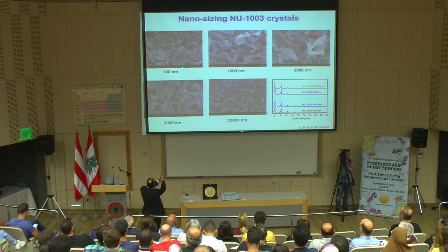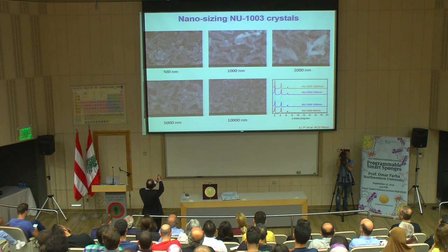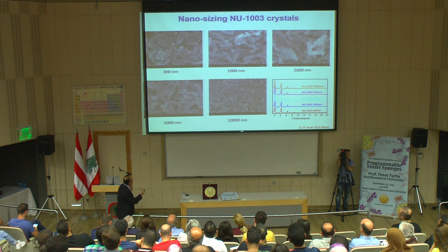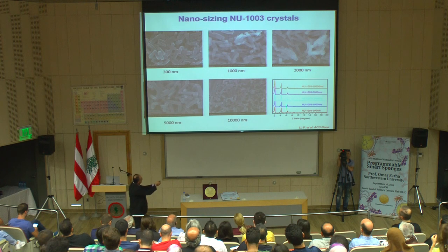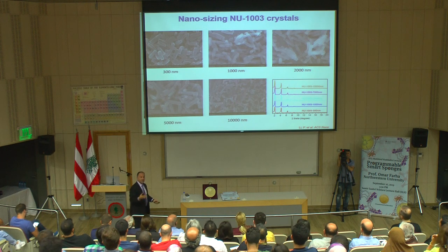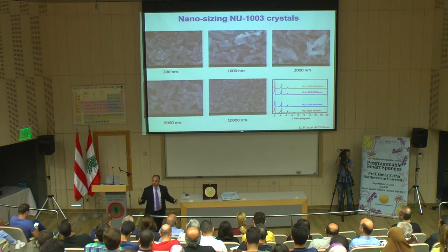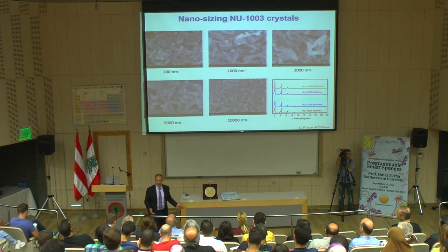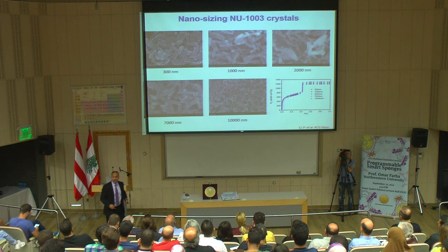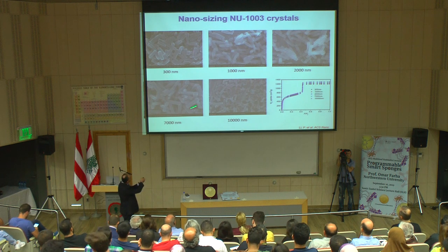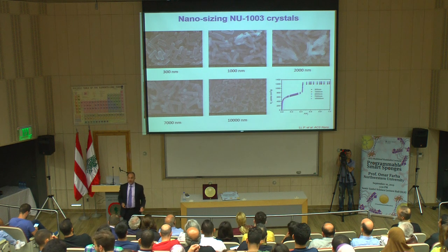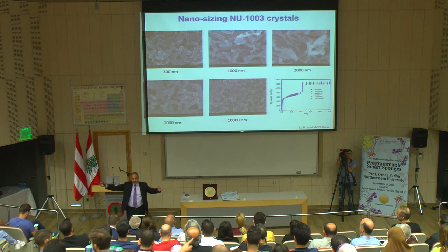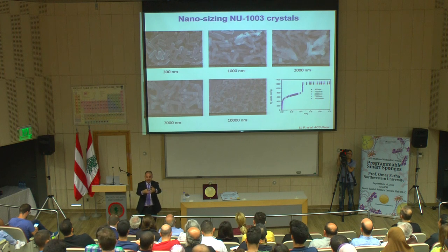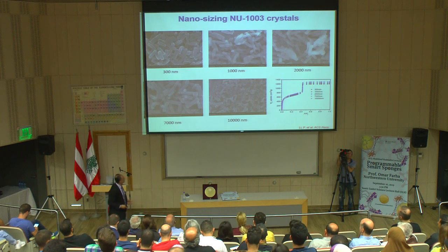You could see we are able to go from 10,000 nanometers or 10 microns all the way to 300 nanometers, and we could make it monodisperse. This is the PXRD. This is the signature that we made the right material. But PXRD can fool you, because if you made anything non-crystalline, you cannot see it. But we test that with nitrogen isotherm, and you could see the porosity of all these materials is almost identical. That means now we made large particles, we made small particles, and things in between, and everything is uniform.